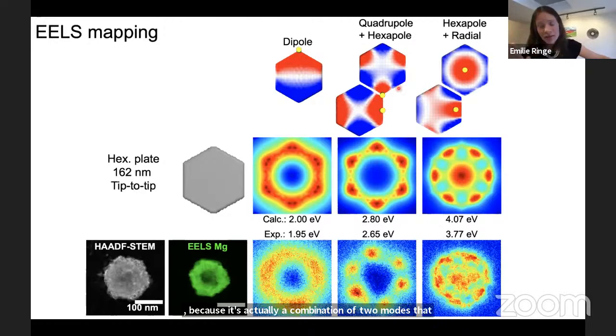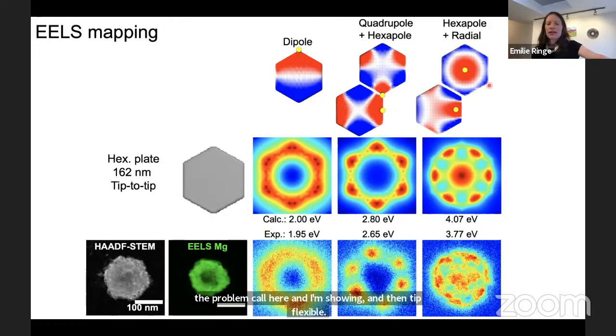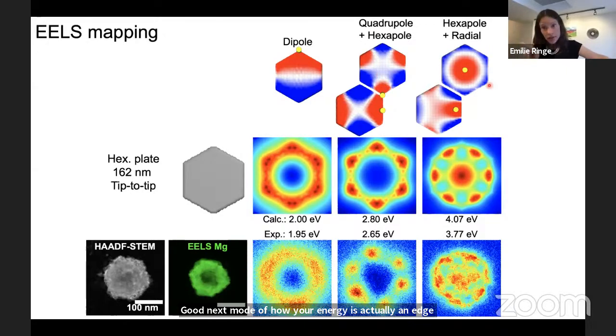They're not degenerate, but they're close and both kind of broad, so they fall on top of each other and there's no way to tease them out. That is the quadrupole I'm showing here, and then a tip hexapole. The next mode at higher energy is actually an edge hexapole, which is not degenerate with the tip hexapole, as well as a radial breathing mode.